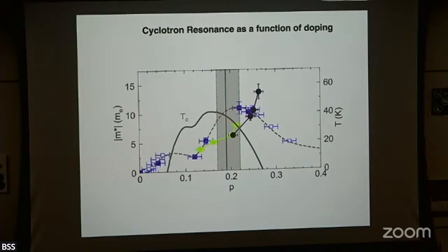One of the things we've done with this is have a long-term collaboration with people at Microsoft who are trying to characterize, for this effort to do quantum computation on nanowires, strong spin orbit coupled semiconductors proximatized with a superconductor on top. It's hard for them to learn about the 2D electron gas buried below the superconducting layer, but we can look through that and see cyclotron resonance. And so it has relevance to interesting materials, but on the industrial side of things as well.